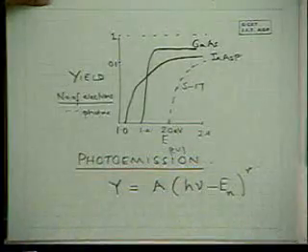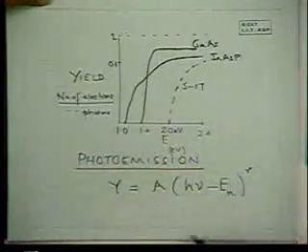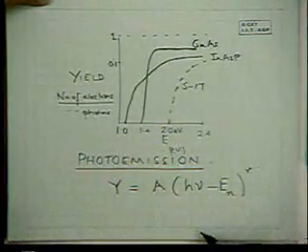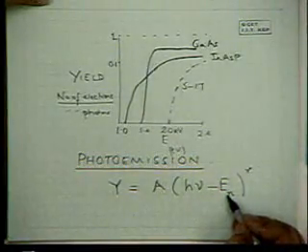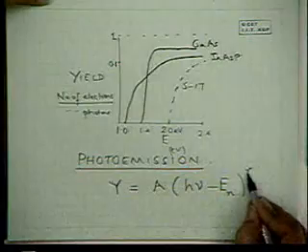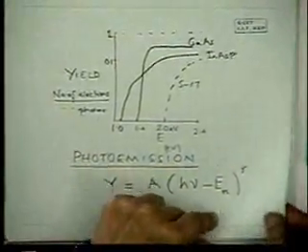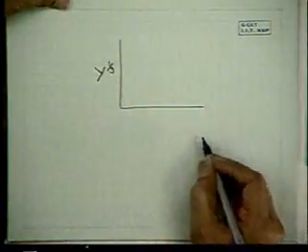And this has been analyzed from the point of view of band structure of semiconductors, and for different direct and indirect gap processes, this value of En is different, and En is just the threshold energy Et, and r is also different. It turns out, if I give you just the experimental data, from the point of view of understanding physics of photoemission, y to the power 1/3 as a function of h nu gives a straight line